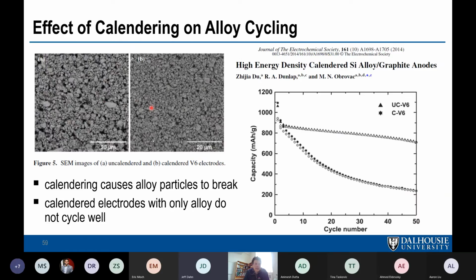The other problem with calendering them, if you remember, is that these things only cycle well if they have a binder that coats all the surfaces, which again is mysterious, but that's true. And if you're calendering them enough to fracture them to reduce the porosity, as you can see here, this is pre-calendered, you can see all the porosity in here, and this is densified somewhat by calendering, by fracturing the particles. And you can see by eye, these are the same coating before and after calendering. The particle size has gone down a lot. And of course, if you're fracturing the particles, now you have particles that have no binder on them, or some fresh exposed surfaces with no binder.